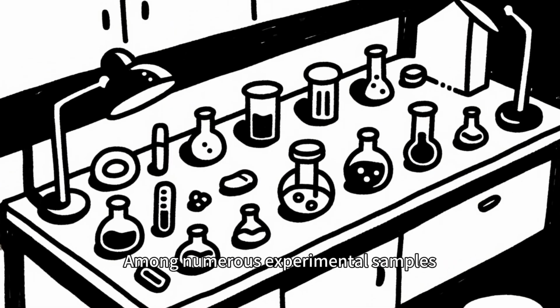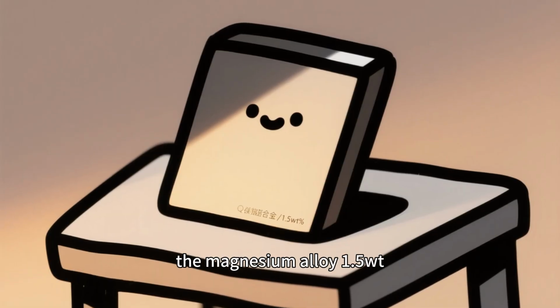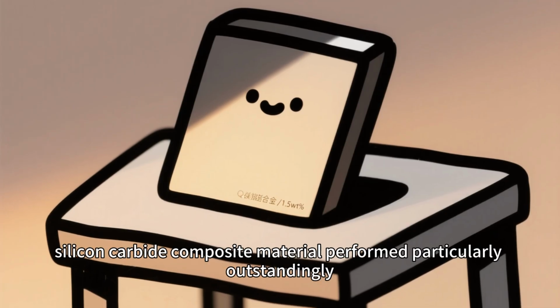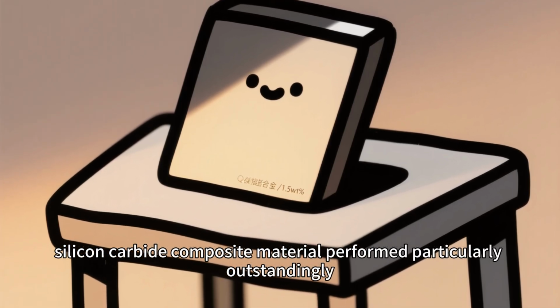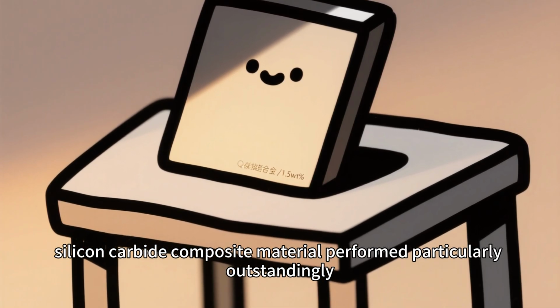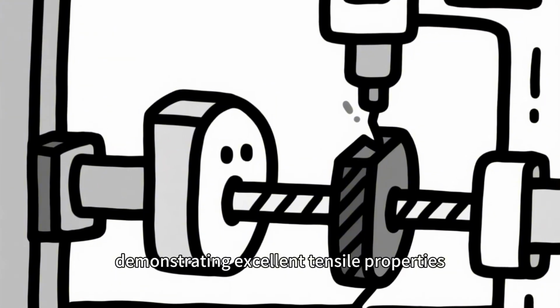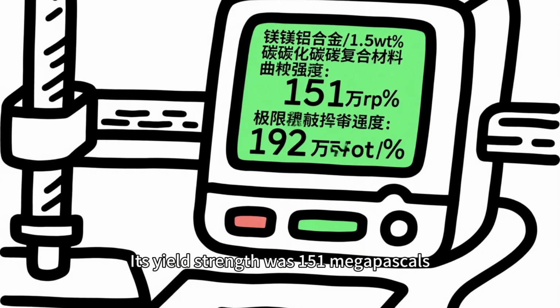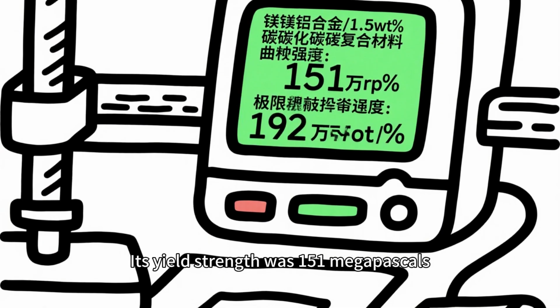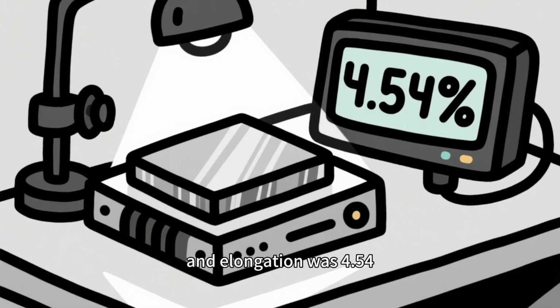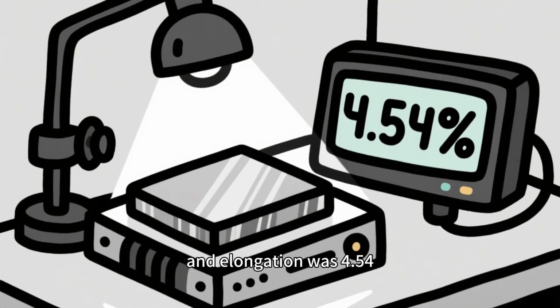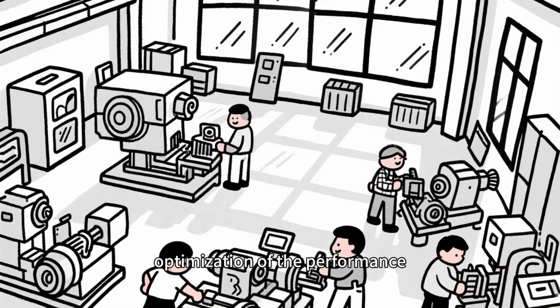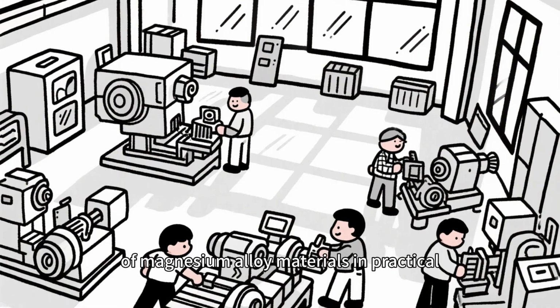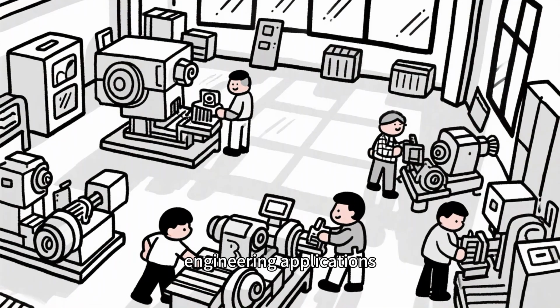Among numerous experimental samples, the magnesium alloy 1.5 wt% silicon carbide composite material performed particularly outstandingly, demonstrating excellent tensile properties. Its yield strength was 151 megapascals, ultimate tensile strength was 192 megapascals, and elongation was 4.54%, which was an optimization of the performance of magnesium alloy materials in practical engineering applications.